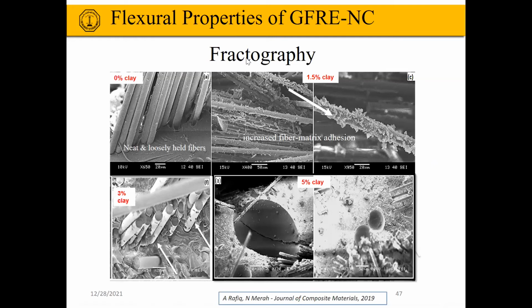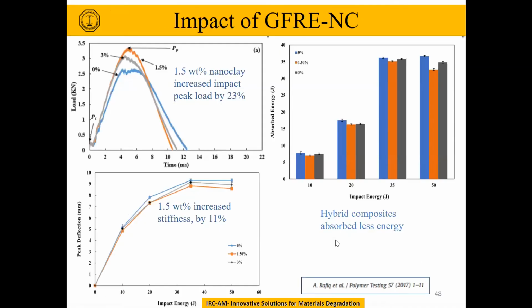Why is that? As you can see, this is 0% clay. You can see that the failed surface has neat and loosely held fibers. But with 1.5%, we can see the increased fiber matrix adhesion. As you go into 3%, you go back almost to the same behavior where we have neat fibers. At 5%, we start having clusters and voids, which reduce the strength of the material.